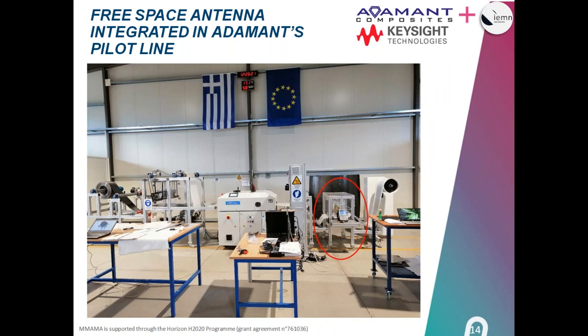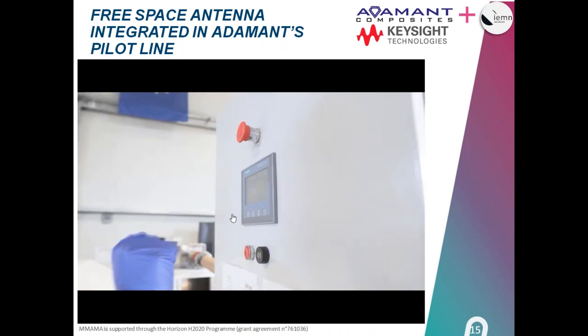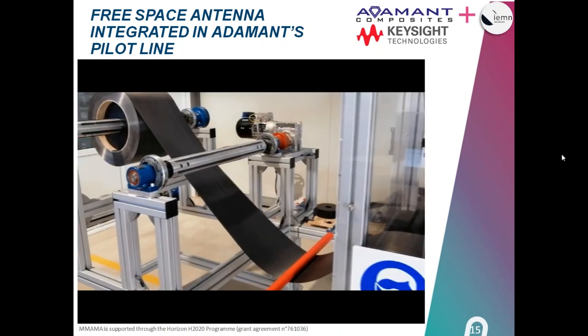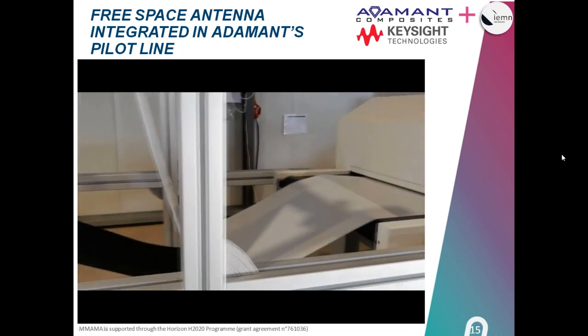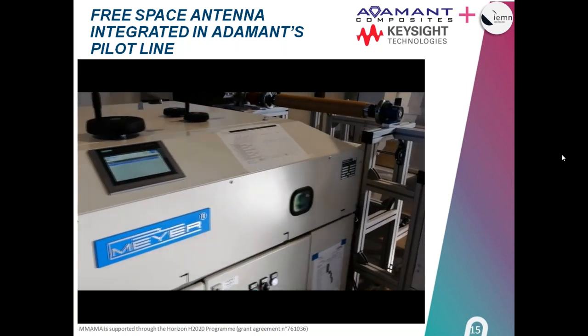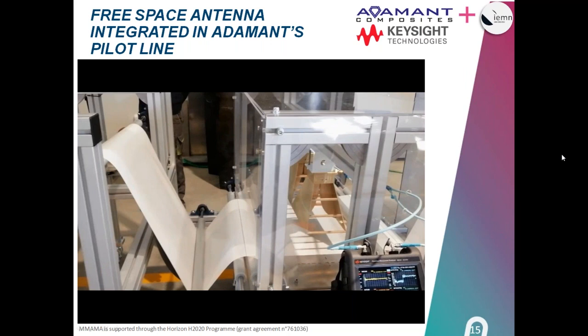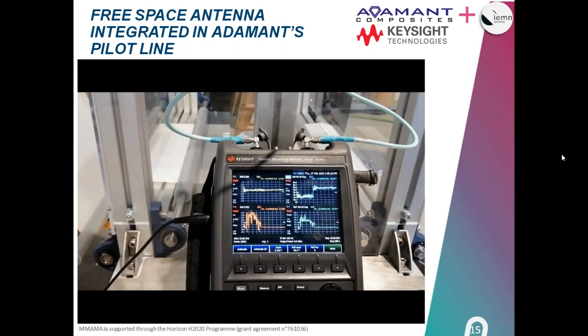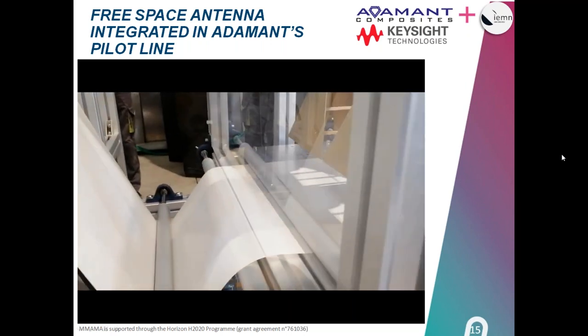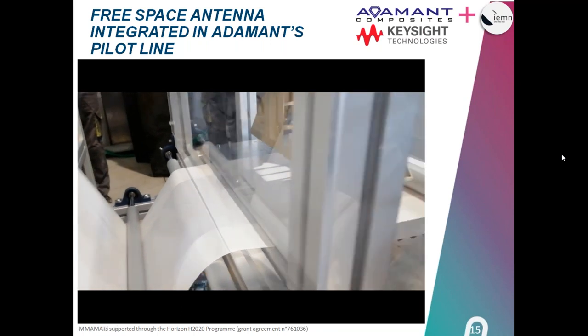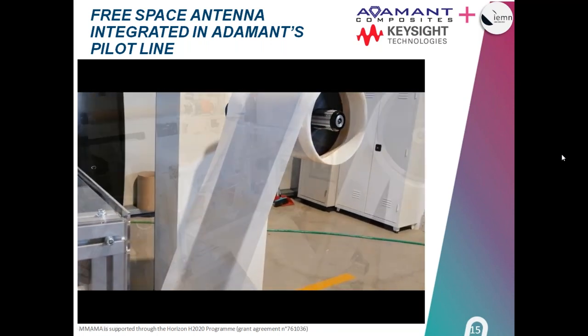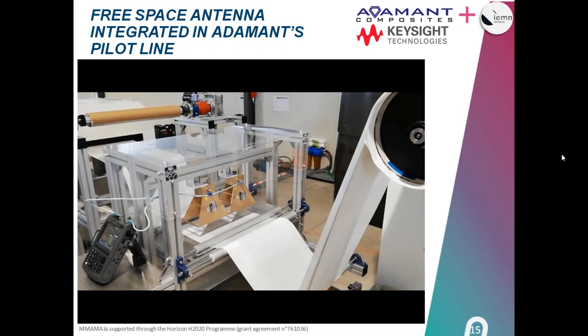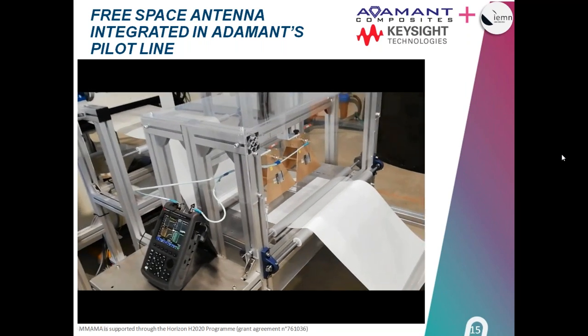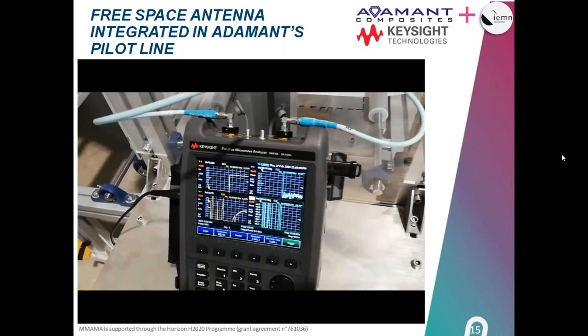Here you can see this platform integrated into a roll-to-roll pilot line at the position control point number three. Here I will present a small presentation of the inline measurement that we did. That's the line. You see the unwinding, the scattering. That's the dedicated machine that we use for the compaction. And now we can see the dedicated module running in real time during an actual production. Here you can see the material is with a protective film, and that's most of the cases for our productions. And that's very nice that we have a contactless method that can measure our materials also using our protective film.